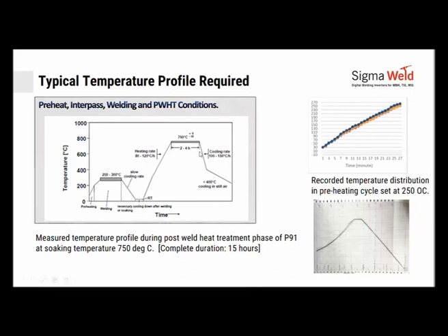Cooling rates are allowed at about 100 to 150 degrees per hour, and below 400 degrees, free cooling or air cooling is allowed. No forced cooling, natural cooling. This is the profile that needs to be achieved, and the same profile can be easily programmed on the equipment. These are some of the examples shown.